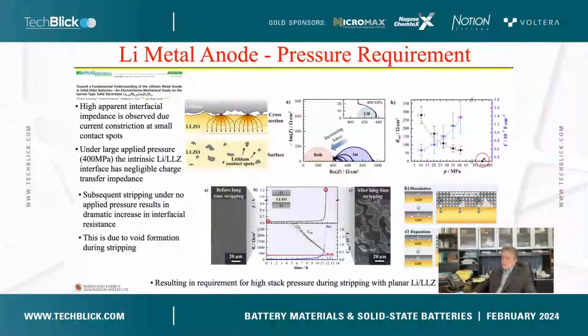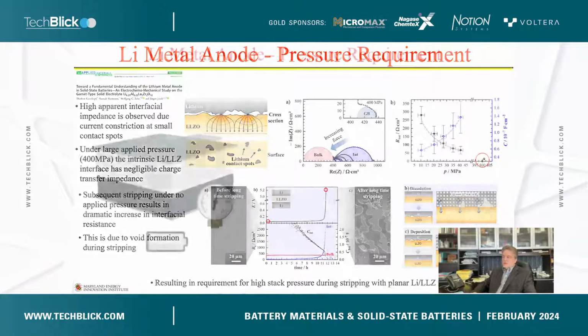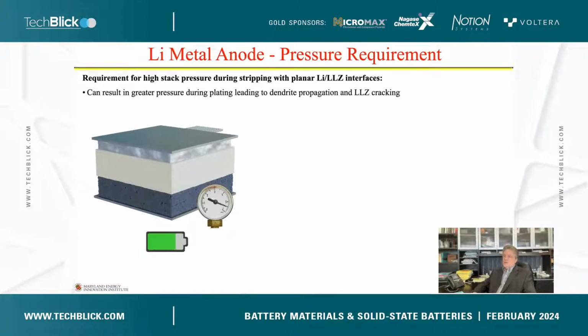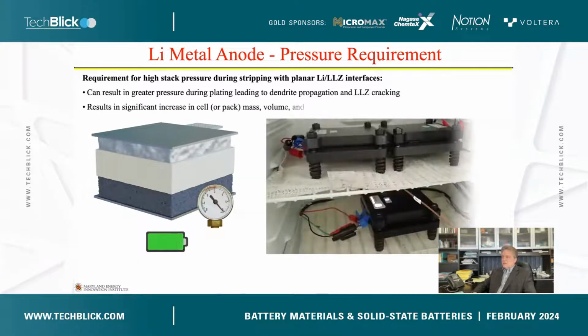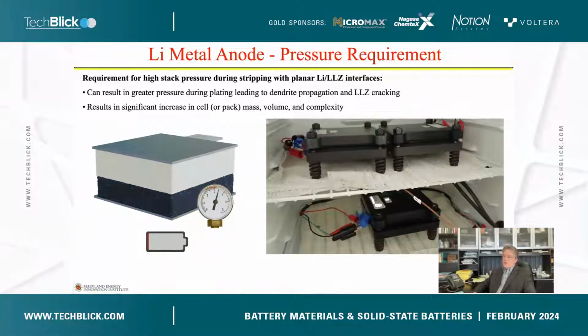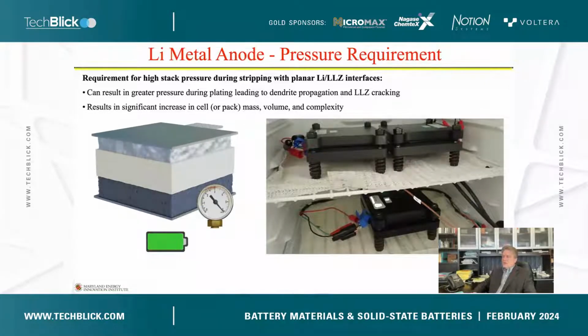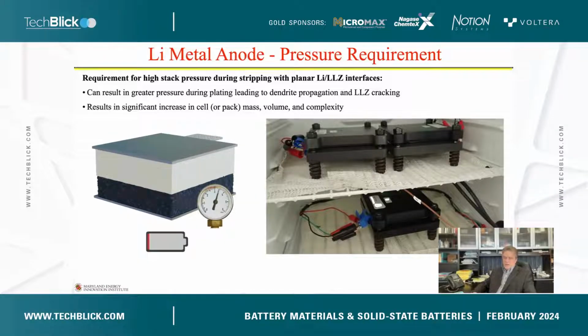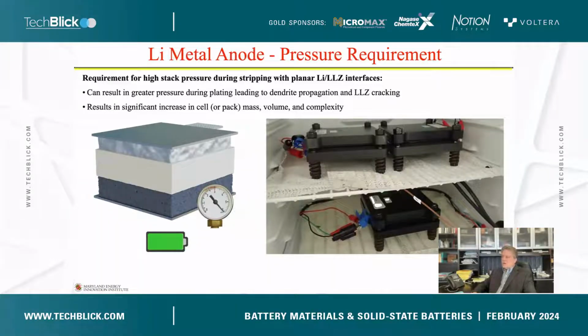Okay, but this results in very high stack pressure required during stripping with planar interfaces. If you have a solid state battery with a solid electrolyte like garnet or any other, you have to apply pressure to it, and you have that infinite volume expansion on every cycle. That can result in dendrite propagation and cracking of the electrolyte. And so the way people address that pressure requirement, as an example, some photographs from the web of QuantumScape's cells, is you apply a lot of pressure, with big giant stainless steel plates and springs and things of that nature. But that to me is not really commercially viable, and we need to find a way to cycle lithium metal with no volume expansion.